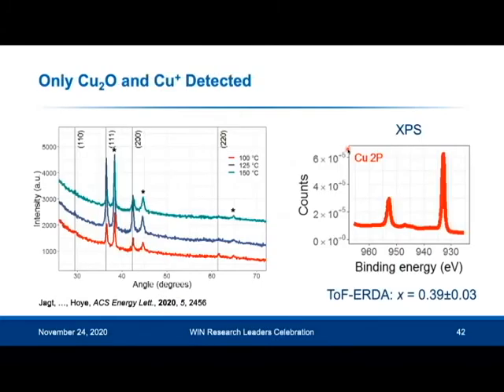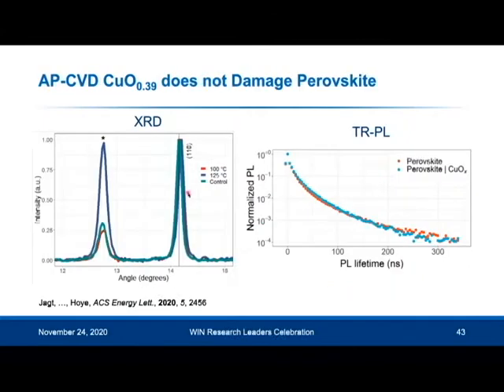We also showed that the cuprous oxide grown was phase pure Cu2O, with copper in the 1+ oxidation state. And we found that we can grow at 100 degrees Celsius, and this avoided any degradation to the perovskite. The total deposition time was about 2 minutes. And we could also avoid introducing any non-radiative recombination channels to the perovskite.